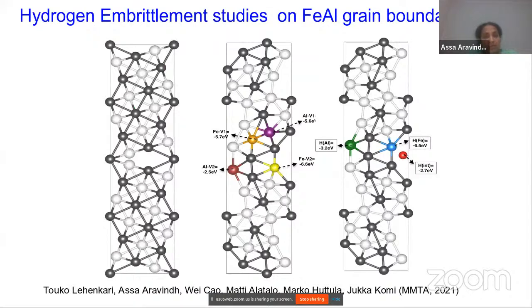Now, hydrogen embrittlement is another very important issue in steel making and also in many alloys, because during the production of these kinds of structural alloys, much hydrogen can get in. So when it goes in, it will stay at some of the lattice sites or interstitial sites, and eventually it can degrade the material. So iron aluminide is a material which is used in many structural applications, and hydrogen embrittlement is a big problem there. And we try to find some insights into it.